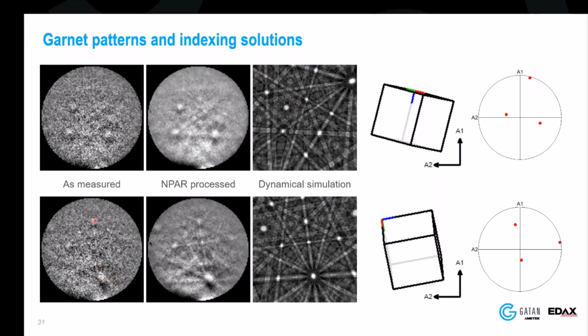So as collected here, I can see a couple of pretty straight zone axes, which is probably enough information, believe it or not, to get a decent Hough orientation. But if I need finer details to get good orientation information off of geological material, this is what we start to see. There's a little band here and a band right here parallel to it. Well, that is these. So this very fine level of detail really helps me get the information here.